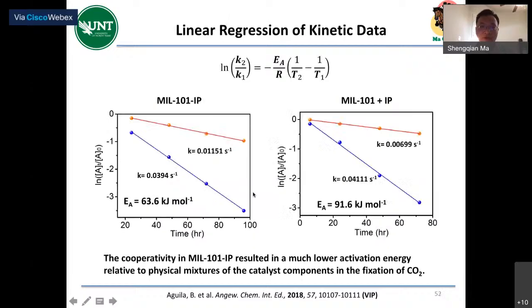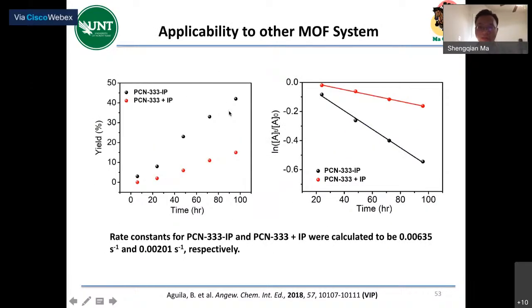And also the MIL-101 we know is a cage MOF, and we can also see using channel MOF, this effect is even more profound. We did it with the PCN-333, the channel MOF, chromium based, and we can see the kinetics and the yield are much more profound. And we found the kinetic constant, when we thread in the ionic polymer in the channel of the MOF, is almost 3 times, more than 3 times actually, the kinetic constant for the physical mixture.